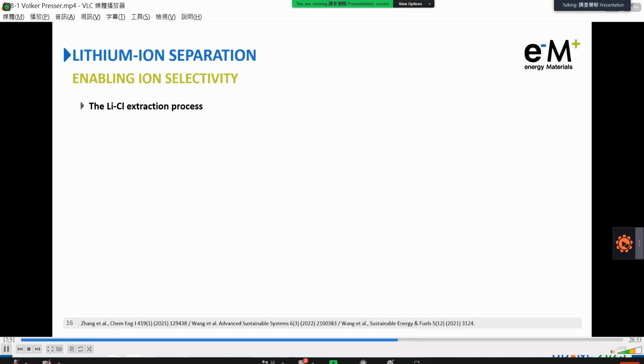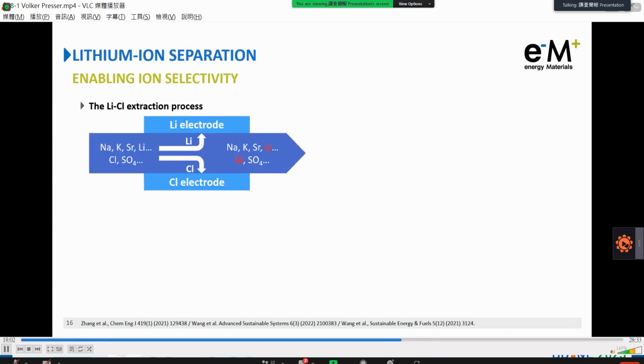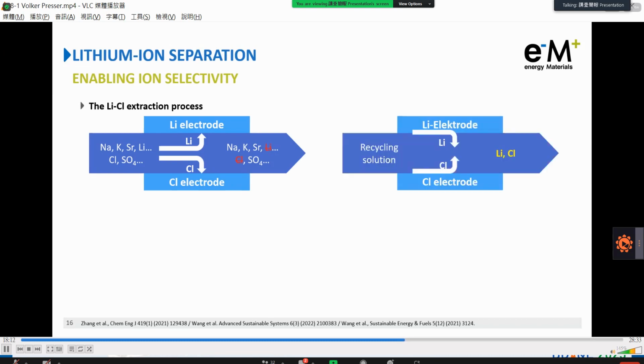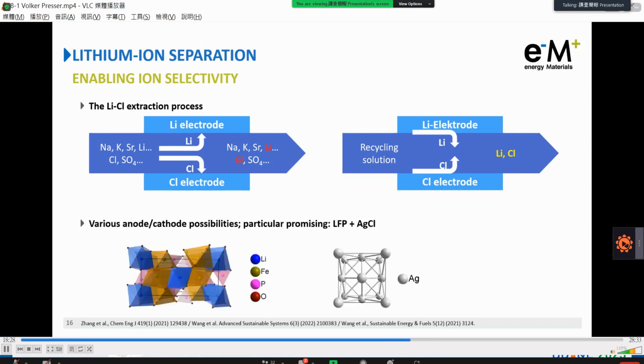There are different ways of capitalizing off of the lithium selectivity of lithium iron phosphate, for example. You can pair lithium iron phosphate with a chloride electrode, like silver-silver chloride redox couple or other systems, whereas by intermittent operation of charging and discharging, you uptake and selectively release lithium and chloride into solutions. This mandates, however, valves that change the feed solution to the recovery or recycling solution between the cycles.